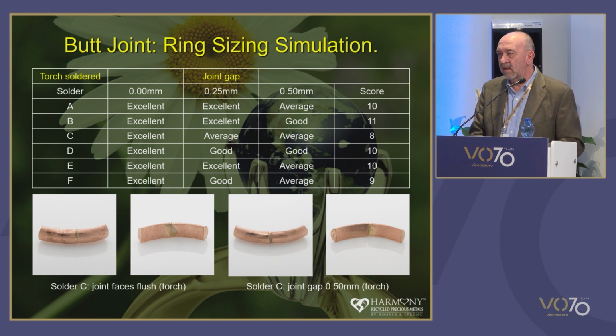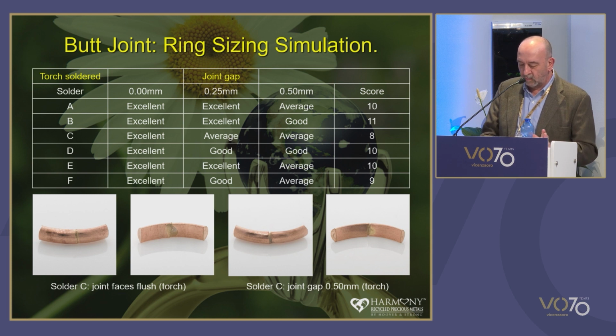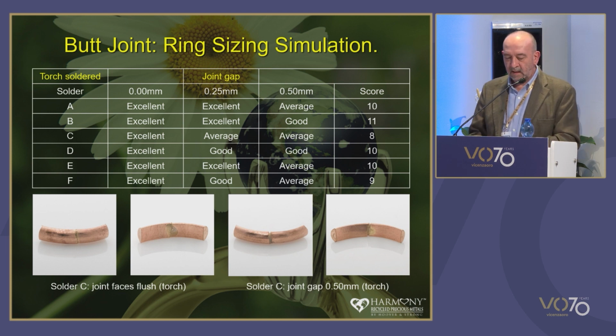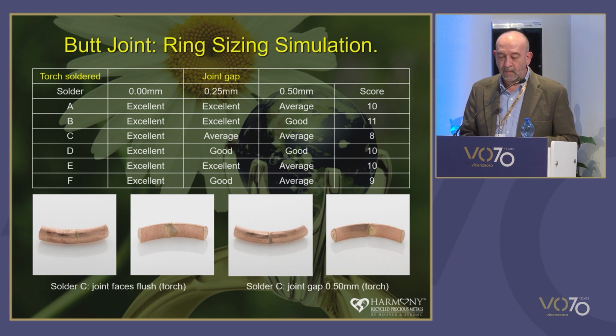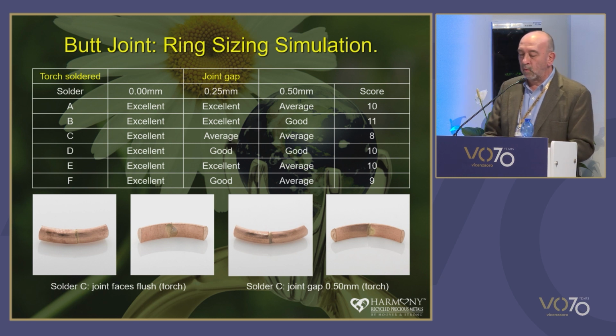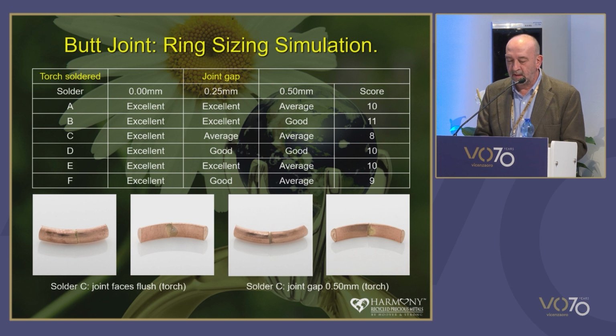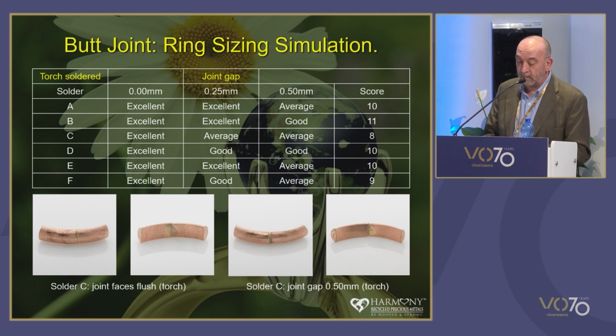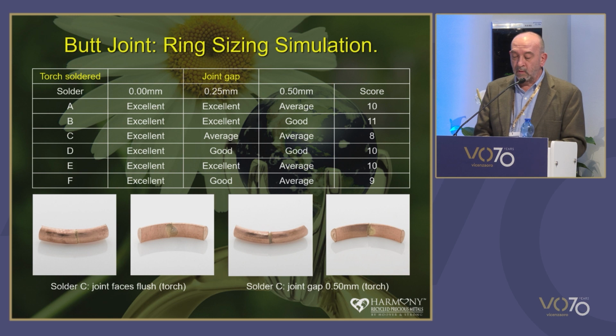We did some microsections and they revealed some minor internal porosity, but it wasn't enough to be considered significant. And they still finished to an acceptable level. The good and the average results for the 1/4 and 1/2 millimeter gap tests were predominantly down to the joint just not filling fully, as we can see on those two right-hand pictures there. Some repair work is going to be needed to fill the joint in, but that could have been possible. For the torch soldered samples, the results were acceptable, except for when the gap became too large. All the test results here can be considered scoring relatively high points.